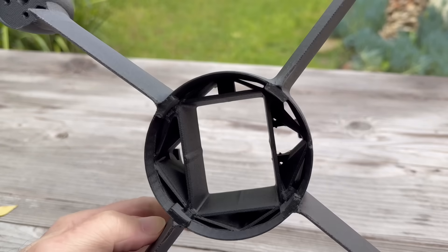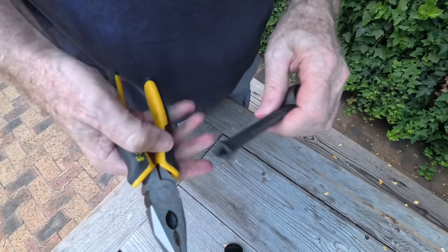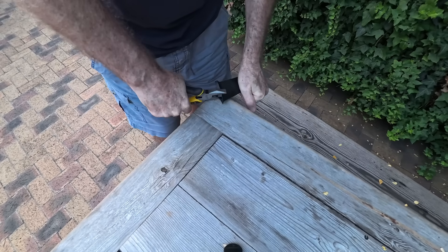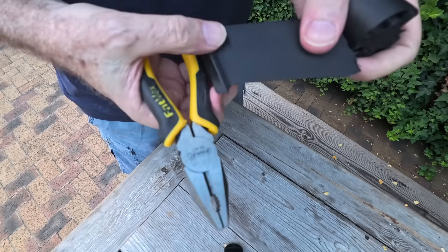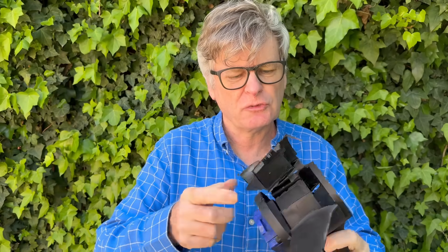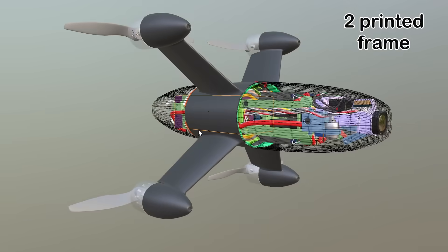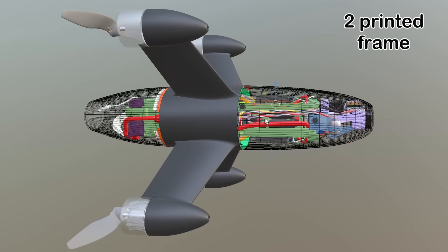We found the Fiberon very easy to print provided you take maximum care to keep the nylon completely dry — the dry box is absolutely essential. We then subjected it to physical abuse testing well beyond what air forces would ever produce. What's useful is that during testing and crashing you get real-life insight into where you haven't got enough stiffness or material, and you can beef it up. Our new nylon body allowed the battery to sit inside the legs, which finally let us position everything pretty much where it ideally needs to be.